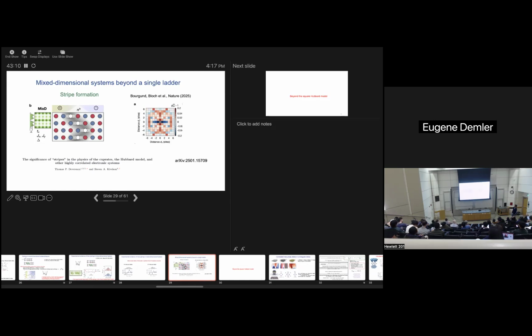And so here, they created basically a collection. You see that there is this bias between different wells, this one and that one. And what they saw is that whereas for one ladder there was a pair that was found, now these holes start aligning up, and so we get a picture of what's known as stripe physics, something that I mentioned before. Again, you can see it in the correlation function. The blue color corresponds to the fact that along the chains, holes are trying to stay away from each other. Whereas this red color means that there is bunching in the vertical direction. In this mixed dimensional direction, holes are trying to line up with the stripe. And that, of course, is the type of physics which is very dear to the heart of Steve and Tom. So now there is a new playground for exploring this.